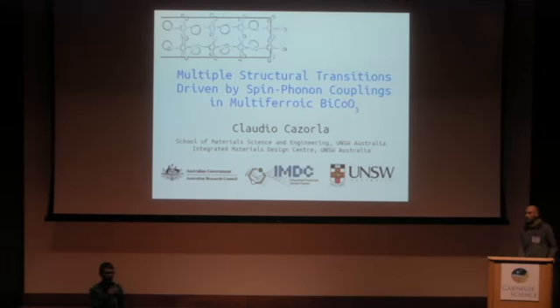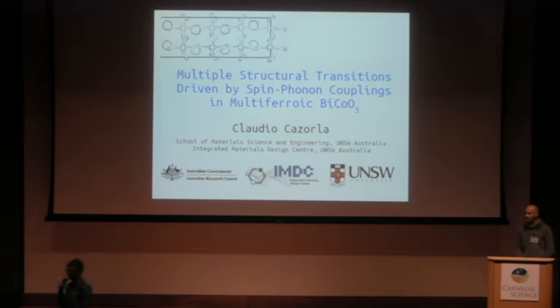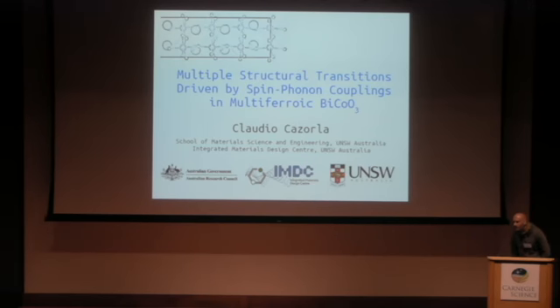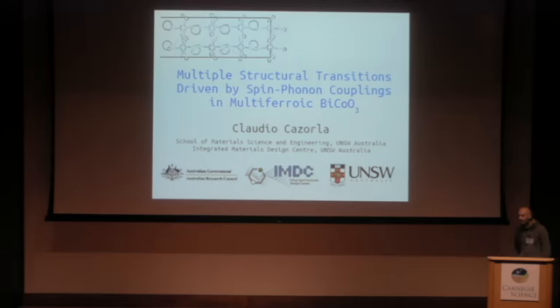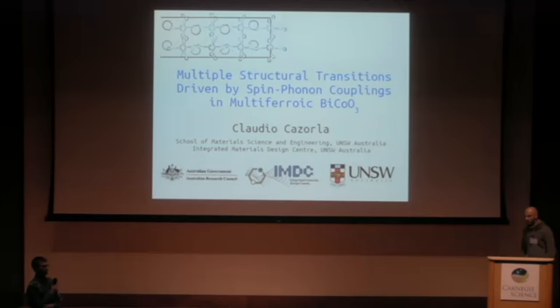Question: As an added level of complexity, did you consider the possibility of spin-state transitions—high spin, low spin, intermediate spin? Reply: Yes, on all these different antiferromagnetic orders, you may simultaneously have intermediate, high spin, or low spin states, and we actually worked on that quite a lot. In the particular case of bismuth cobaltate, it's a bit controversial whether it's high, intermediate, or low spin. We checked all those possibilities and discussed it extensively in the supplementary information of our last paper.